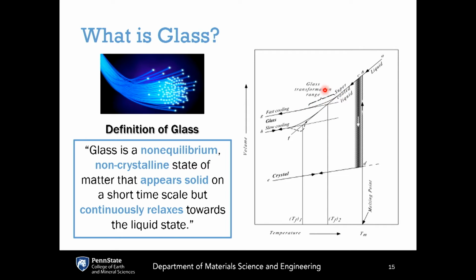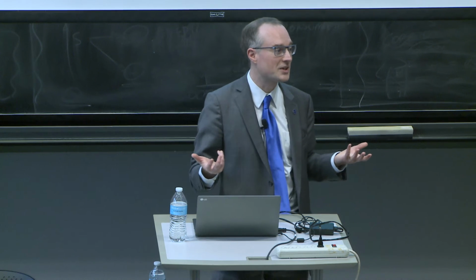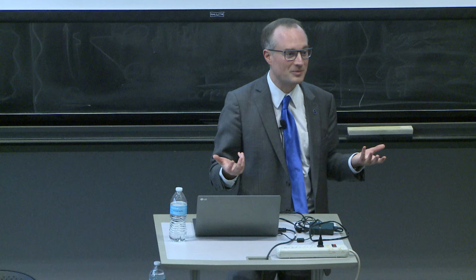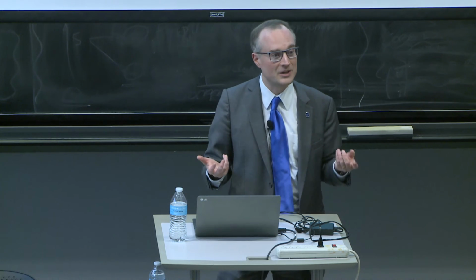It's going through what's called the glass transformation range or glass transition range, freezing in so that these configurational transitions of the atoms are no longer possible on your time scale of observation. You get a material that has the frozen-in structure of a liquid that, for many practical reasons, behaves just like a solid. If you drop it, it might break. But its structure is that of a liquid. And this material is what we know and love as a glass.